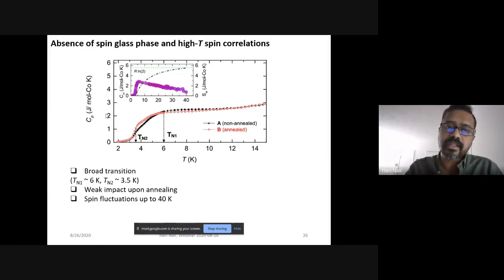Now, if I calculate the magnetic specific heat out of this total specific heat, I see indication of magnetic specific heat or entropy existing all the way to 40 Kelvin or so. Which means that the entropy is not completely removed at TN or TN1 or TN2, but exists even up to high temperatures. It means that the spin fluctuations or the correlation functions are relevant even at those high temperatures, and it doesn't saturate at a value of R log 2.